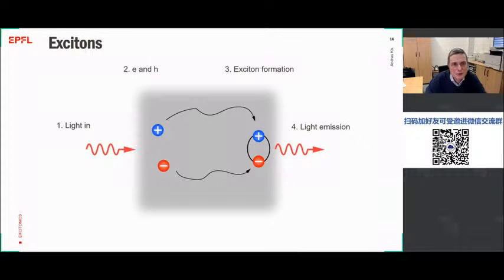So the excitons in semiconductors are formed when you excite them with light. So if you shine light on a semiconductor with energy which is above the band gap, then you're going to generate electrons and holes at the band edges. These can become free in the material, or they can form an exciton, which is a state where the electron and hole are attracted to each other. This exciton has a certain lifetime, and when this lifetime expires, then the electron and hole recombine, they annihilate each other, and you get light emission and light coming out of the material. And this is, for example, what you could have in standard photoluminescence.